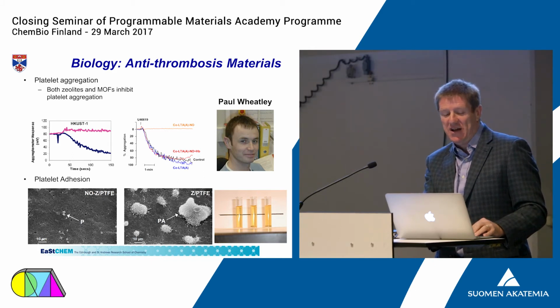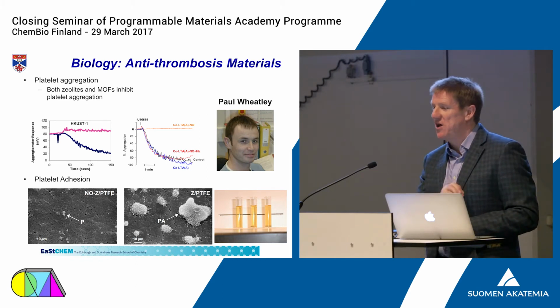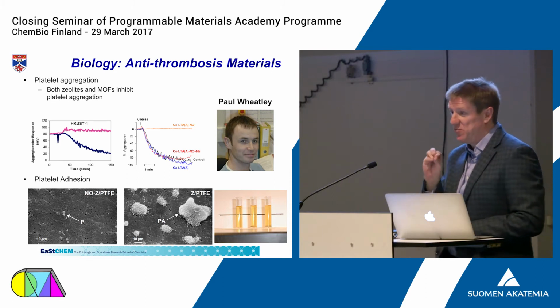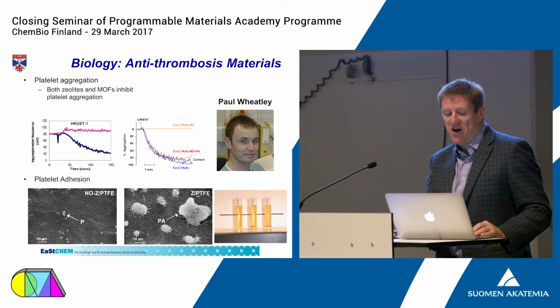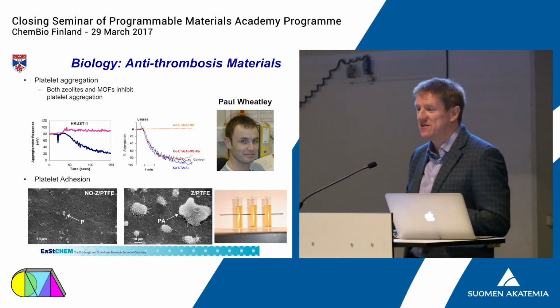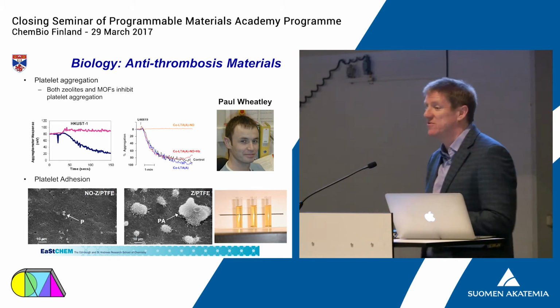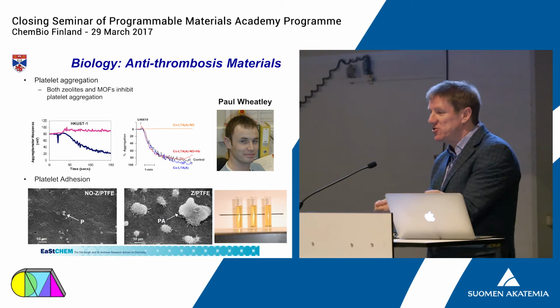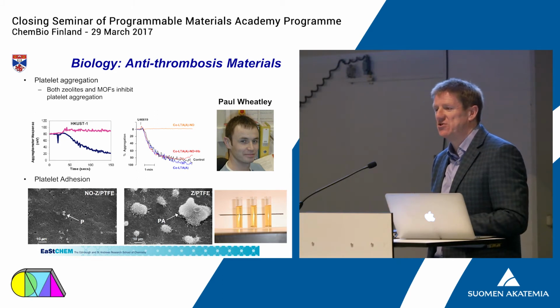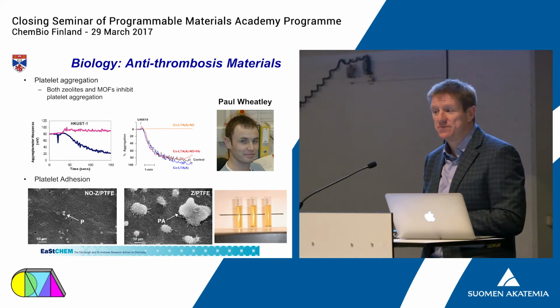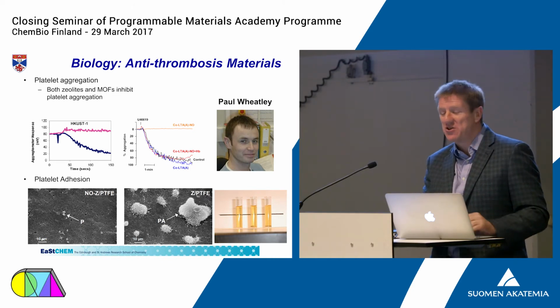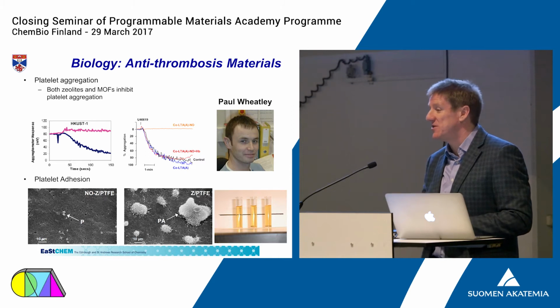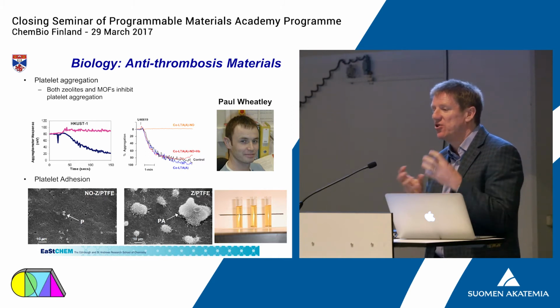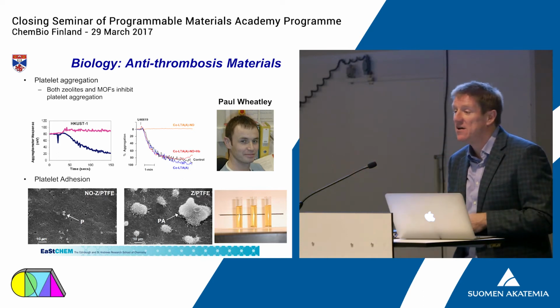And the actual pictures are even better, I think, because they show that if there's no nitric oxide being produced and you put it in contact with Paul's blood, with Paul's platelet-rich plasma, you can see that there are sort of angry little clumps of platelets that have stuck to the surface. That's what happens when you put a medical device in, often, into the blood. You switch on the platelets, the foreign surface switches on the platelets, you can get thrombosis. Microthrombosis in this case. If there's nitric oxide there, it completely stops that aggregation process, and you can only see just single platelets sticking to the surface.